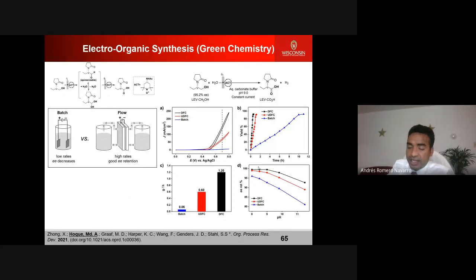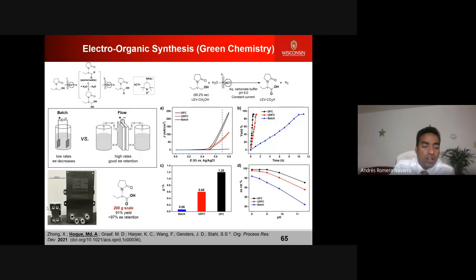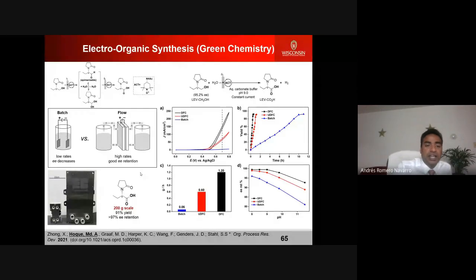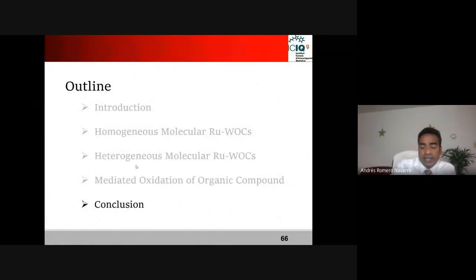And in industry, they think of scaling this up and selling that compound, right? All this chemistry I'm showing is in a flow cell which is small in size. But if you want to scale up, you just need to increase the size of your reactor. And that is exactly what we did. We synthesized 200 grams of this molecule with 91% yield and enantiomeric excess retention above 97%. This is the work of my postdocs, and I'm presenting it partially.